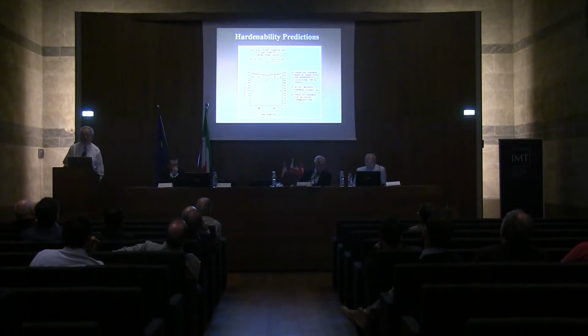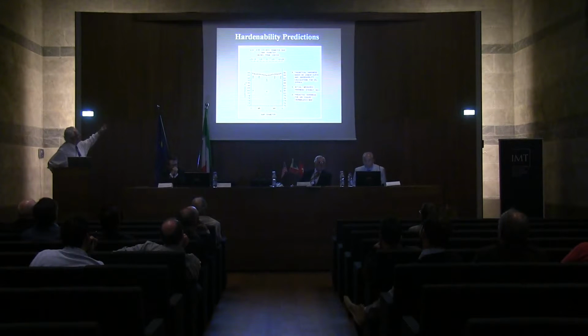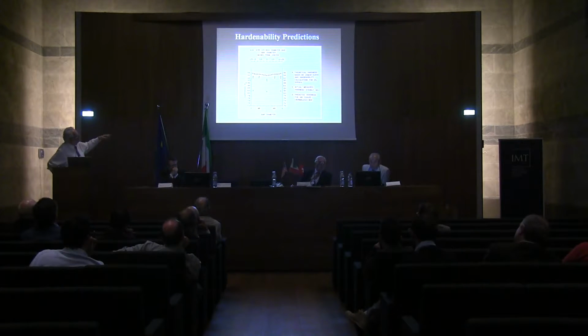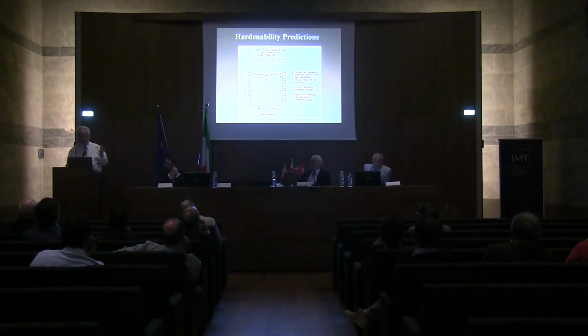Now, here's another example. This is 1035, 2.5 inch diameter bar. And you can see you've got the bar diameter across here on the bottom: surface, mid-radius, and center. The hardness in Rockwell B is on the y-axis. Now, the theoretical hardness based on the geometry curve and hardenability calculations for an oil quench are the circular data points at the top. And then the actual hardness are the squares measured on the eye bolt. And the triangles down here are the predicted hardnesses if we had air-cooled it based upon the geometry data, right? And you can see the air-cooled hardnesses are down around 82 Rockwell B. The actual hardnesses are much closer to the theoretical for oil quenching.